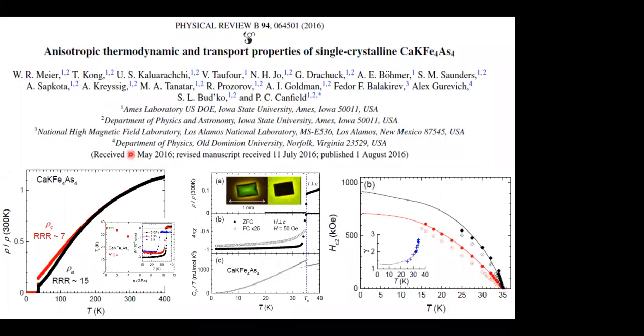Okay? This is a material that has simply a superconducting transition. No magnetism, no orthorhombicity, but it has a beautiful sharp Tc. In the single crystals, we could push it up to 35 degrees Kelvin. It has a large and mildly anisotropic Hc2, and it's not that different in behavior from what we saw for the original potassium-doped barium 122.